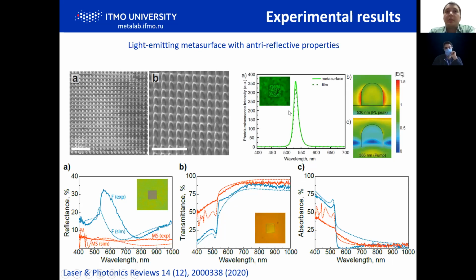Interestingly, after processing by focused ion beam, which is a very harmful method for light emitting structures because it generates a lot of defects in the remaining material, indeed after direct cutting we have a very low photoluminescence yield. But after some post-processing we recover the photoluminescence yield, and you see here that the metasurface demonstrates even higher photoluminescence because of resonant behavior, because of Mie resonances around the photoluminescence, so it's due to the Purcell effect.